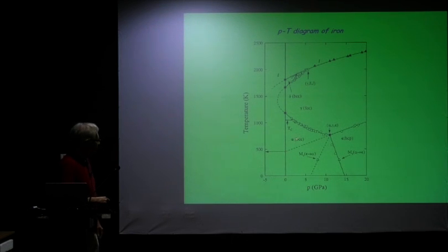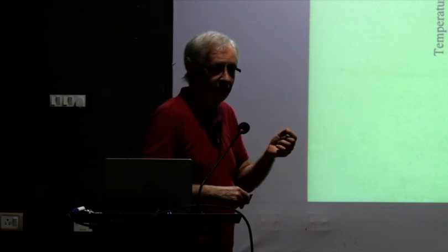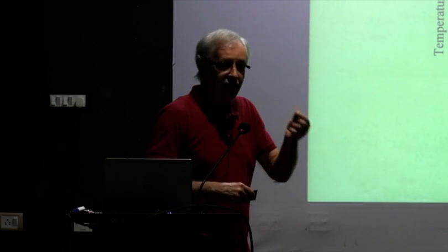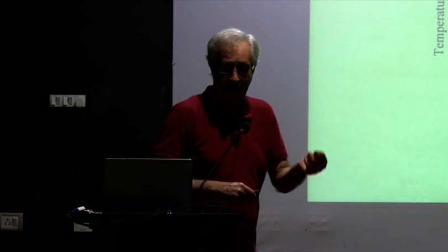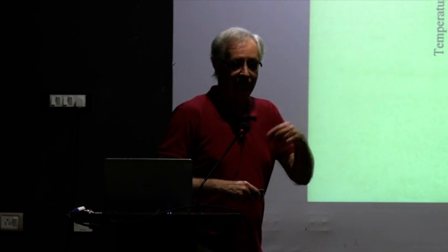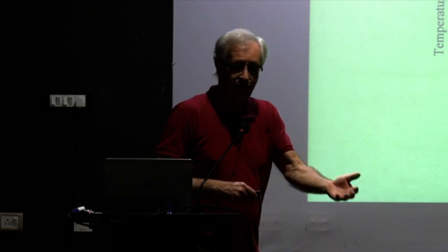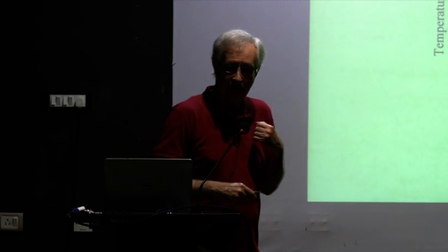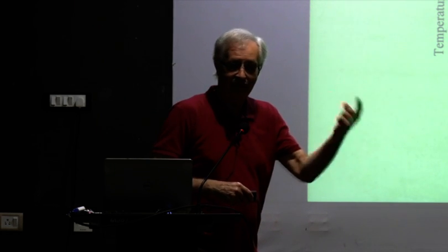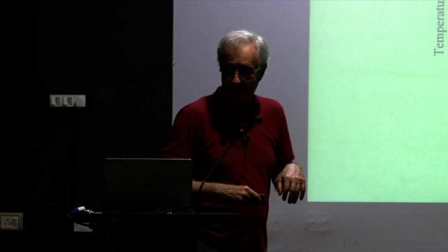Same thing goes for BCC iron, that at zero pressure, the epsilon phase would have been the most stable phase if BCC were not magnetic. What stabilizes the BCC state is the magnetism. So if you take away the magnetism of the BCC state, it's not the FCC state that's stable, but it is the hexagonal state that is stable.